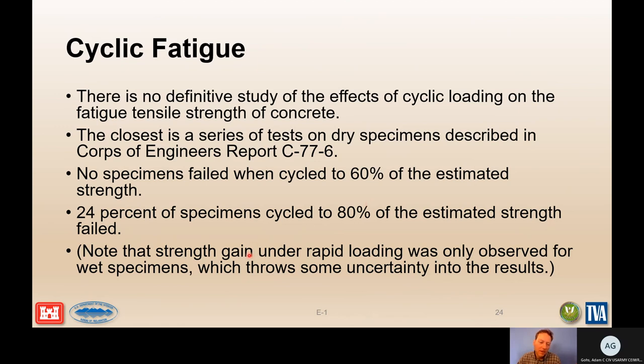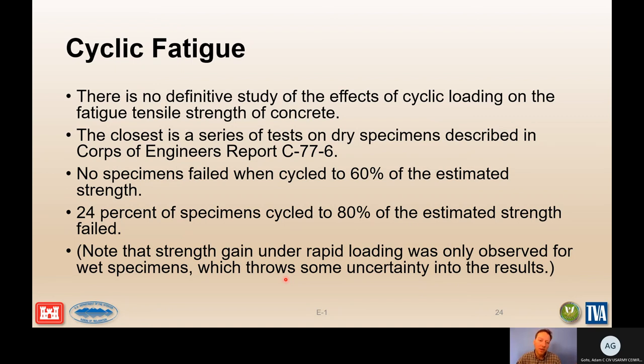The Corps report also noted all samples were dry, and dry samples under rapid loading showed no strength increase, whereas wet samples did show a dynamic strength increase. This is consistent with other reports, though that dynamic increase is somewhat controversial — it may come from pore water pressures taking additional load. Be careful not to account for that strength increase in very dry concrete. In this context we're usually talking about concrete dams, which are typically wet, so the increase is often taken.